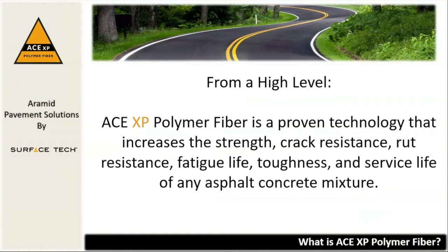So how do we get these lightweight Aramid fibers into the asphalt? Good question. Aramid needs to be treated in order to get it into the mix with the aggregates. The combination of Aramid polymer and treatment is what we call ACE-XP polymer fiber. ACE-XP polymer fiber is a proven technology that increases the strength, crack resistance, rut resistance, fatigue life, toughness, and service life of any asphalt concrete mixture.